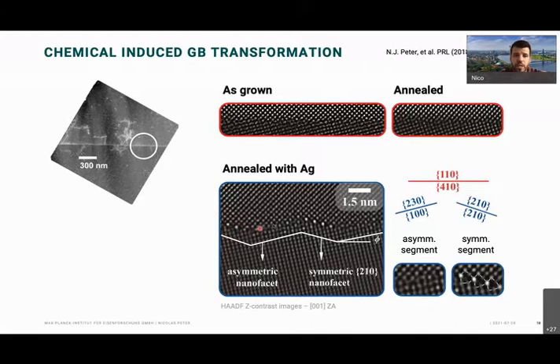We have a boundary that runs in a zigzag way. And what we can see here is also, this is preferential segregation. So one part of the facet is silver free. One is decorated with silver, and you can see it by these bright dots. So these are HAADF Z contrast images in STEM. And you can see all these bright dots are a higher Z number material, which is likely the silver.